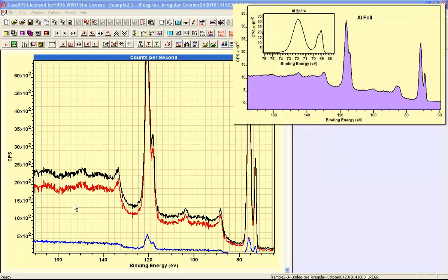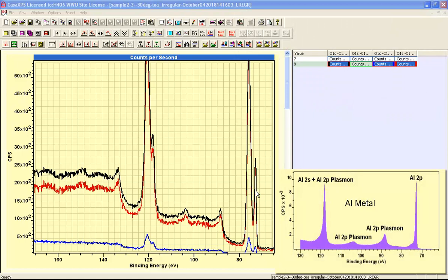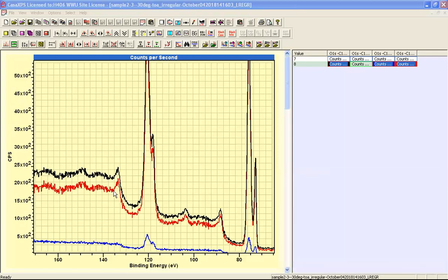After these two components, the red one is interesting in as much as it looks very much like a surface layer of aluminium oxide on aluminium. You can see we have the aluminium metal peak here and corresponding plasmon peaks. Aluminium 2s similarly has plasmon peaks. So put together, this has a strong appearance of aluminium oxide on aluminium metal.